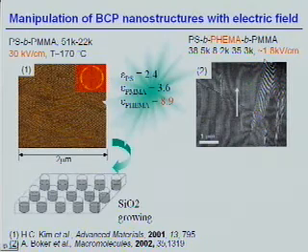So how can we use this nanostructure after you aligned? If you obtain this nanostructure that you like in block copolymer, then how can you use it in real manufacturing? As we can see, this is an example. We can remove the areas of one of the blocks. For example, in this picture, we can remove the PMMA block. Remove these light cylinders. Then many aligned, ordered nanopores are created on such a film.